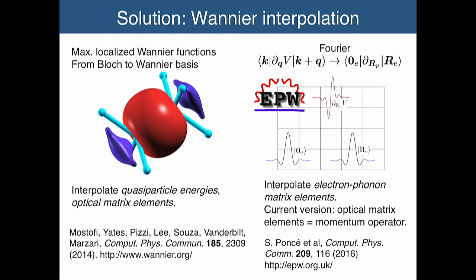I want to make a comment here in that when you have a pseudopotential, the momentum operator is not the right operator to use. We have to use the velocity operator that is independent of your pseudopotential. And we're working on changing that. The two of them typically differ by a small factor, but we will have the velocity implemented soon as well, because the velocity can be interpolated with the Wannier basis as well.